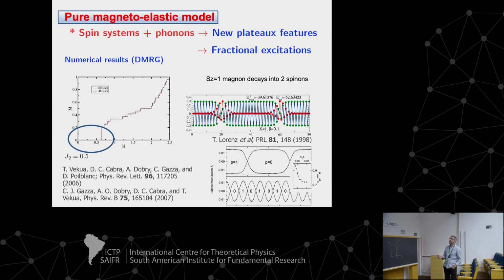But let me just discuss this simpler case. If you look at the purely magneto-elastic model, what I call the spin-phonon Hamiltonian, you have spins and phonons. Here these are just classical deformations, but it can be extended to the more general phonon case. We studied this a long time ago with Poilblanc and some of my collaborators when I was in France. And we saw interesting features in the magnetization curve once you consider these elastic degrees of freedom.